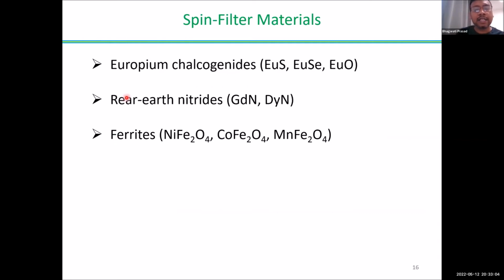Other spin filter or ferromagnetic insulator systems are the gadolinium nitrides or dysprosium nitrides. These nitride systems have been worked on by Mark Blamire's group from Cambridge, my supervisor's group. But these materials are also very tricky to grow. You have to encapsulate them. They have low TC, the same issue.